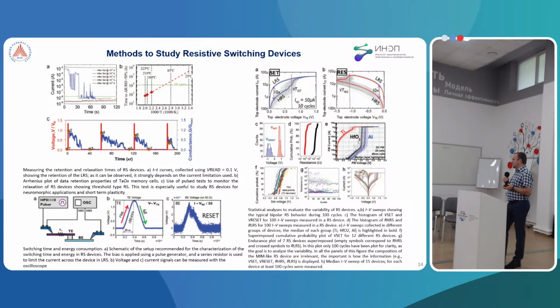The next method to study resistive switching is statistical analysis to evaluate the variability of the resistive switching device. We measure current-voltage sweeps showing the typical bipolar resistive switching during, for example, 100 cycles or 1000 cycles.